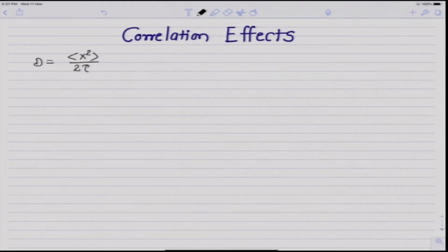If we consider the mean square displacement, which is denoted as average r square, it can be given as average of x square plus average of y square plus average of z square. x, y, z here denote the projections on the x, y and z axes of the net displacement vector r. In isotropic diffusion, the distribution is spreading equally in all directions.